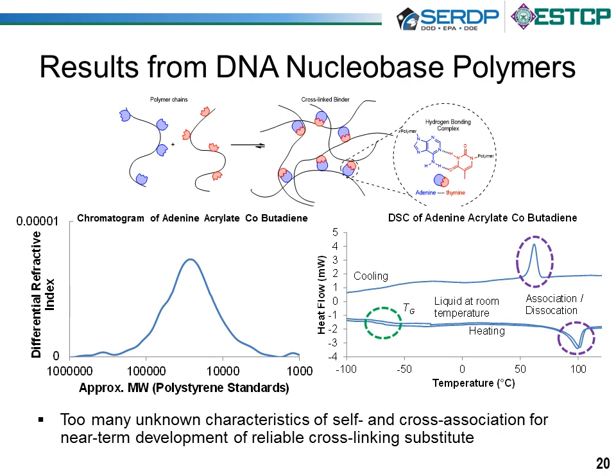These things have to be low viscosity liquids so that we can mix them in with the energetic materials and the propellant. And the bottom line is that although one of these two materials is a low viscosity liquid, the other one is not. So you really are unable to mix these together the way that you would like. What that means is that while it's an interesting system and deserves some further study, it's not really ready to be considered as a candidate replacement for isocyanates yet.